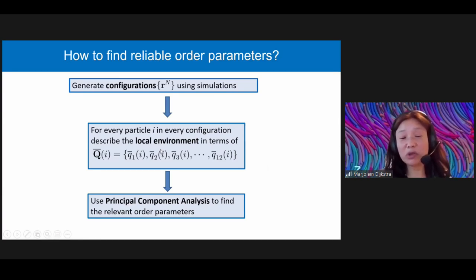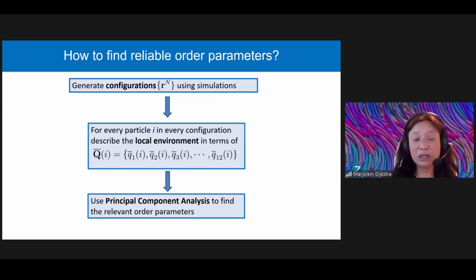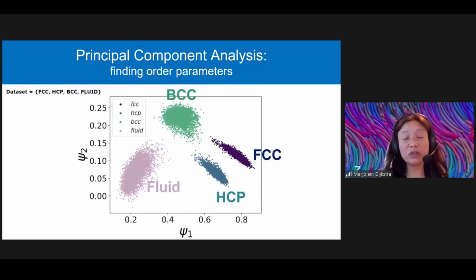And then we use a principal component analysis, which is basically a linear transformation of the basis, to find the relevant order parameters. This new basis set is constructed in such a way that the first principal component accounts for the largest variance in the data set, and then the second largest. If we do that for typical fluid, HCP, FCC, and BCC configurations, we find that these clouds are very nicely separated from each other.